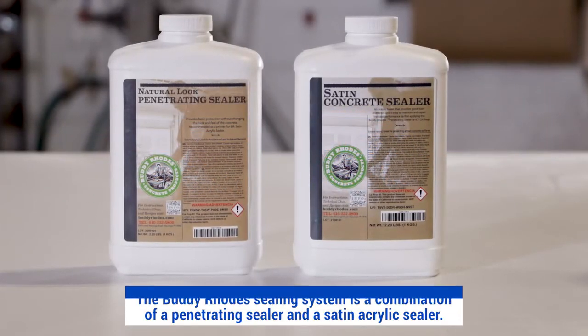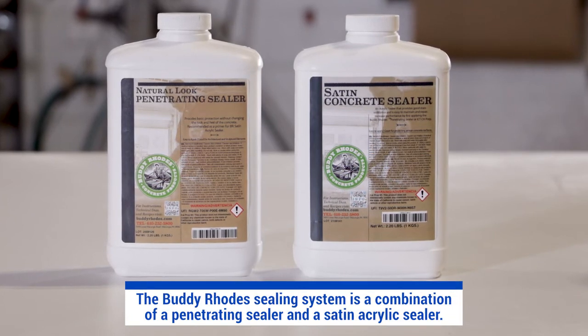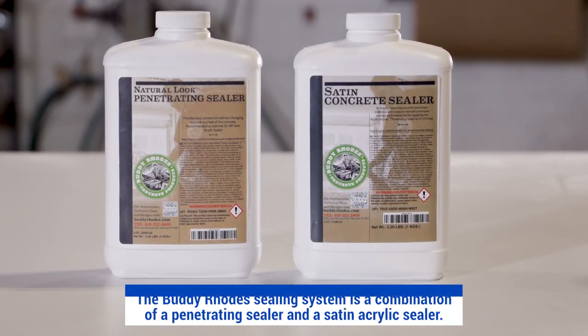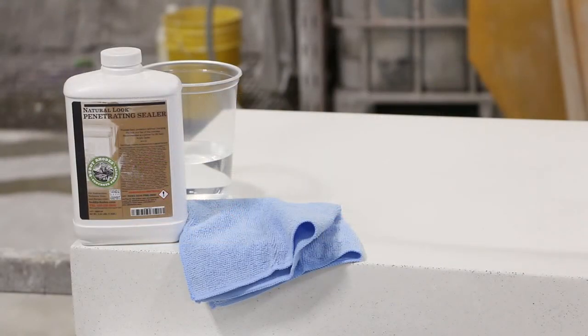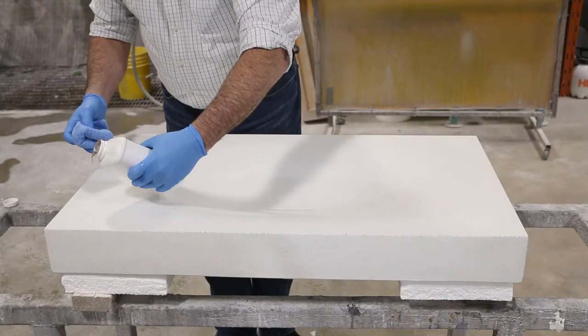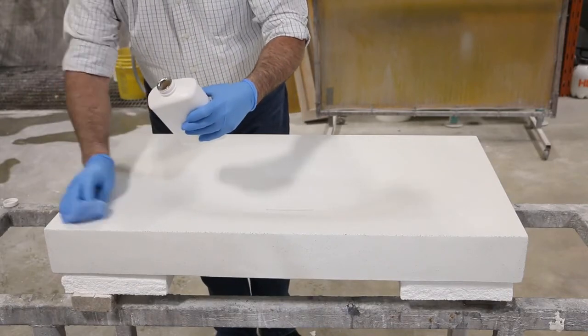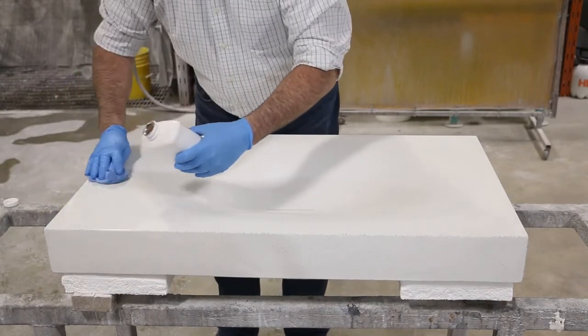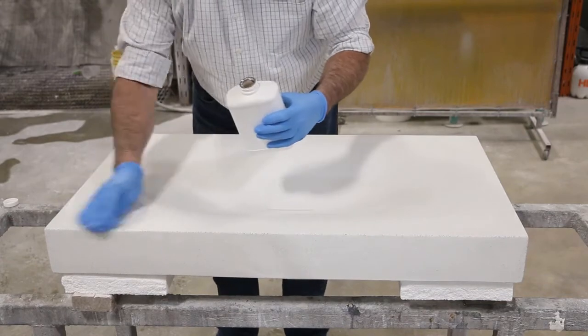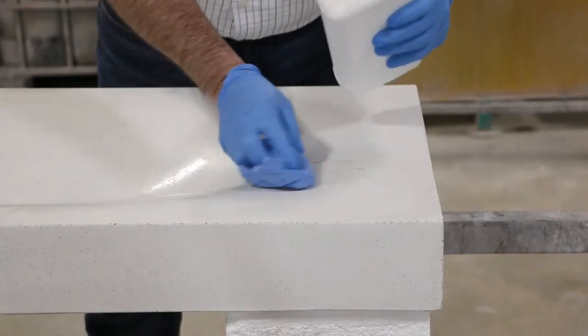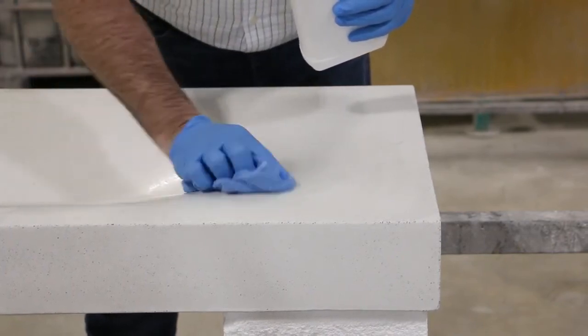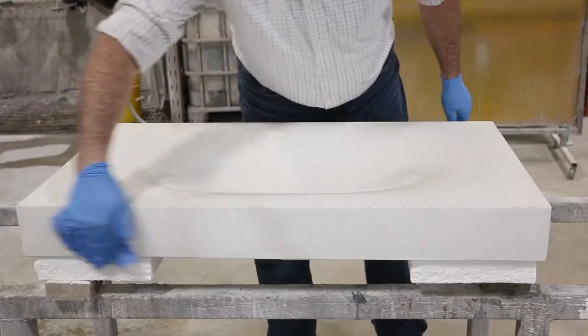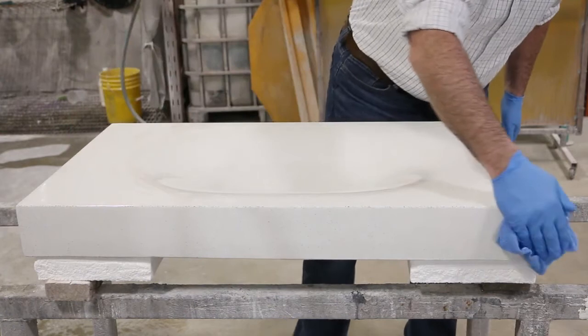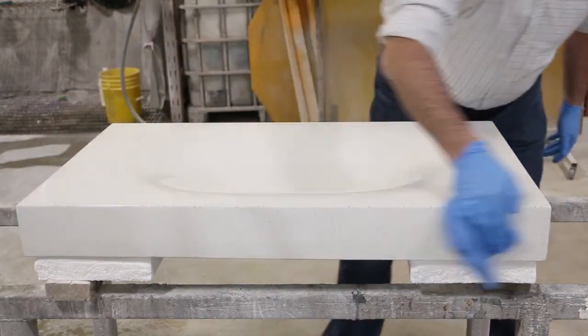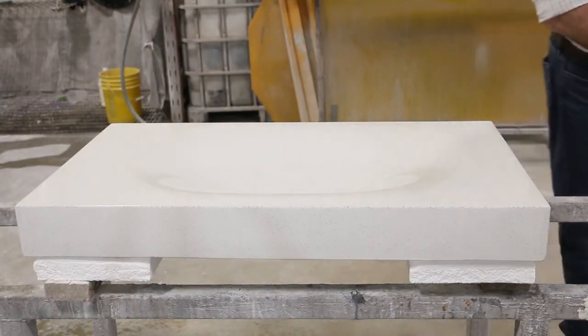For this sink, I chose the Buddy Rhodes Classic Sealing System: Buddy Rhodes Penetrating Sealer and the Satin Sealer. First, we apply the penetrating sealer using a damp microfiber cloth and apply liberally to allow as much penetration into the concrete, keeping it wet for a few minutes. This is allowed to dry.